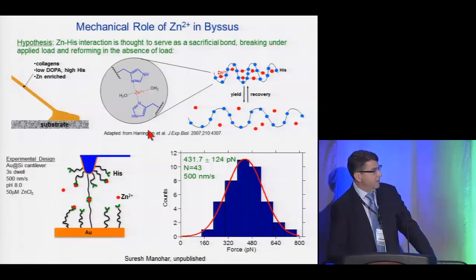And you can see some of the preliminary data here that we have, which gives us bond ruptures in the 400 piconewtons range, which again is very, very large for a single molecule observation. So these are likely also the interactions between zinc and histidine in this tissue are also likely to be very mechanically active and contributing to the mechanical properties that we observe of the tissue.